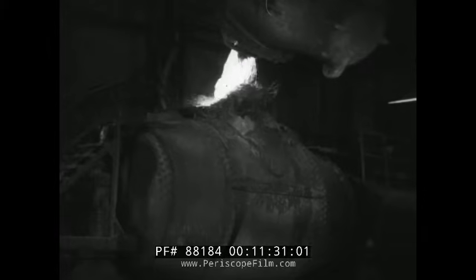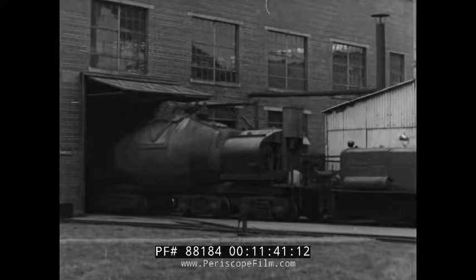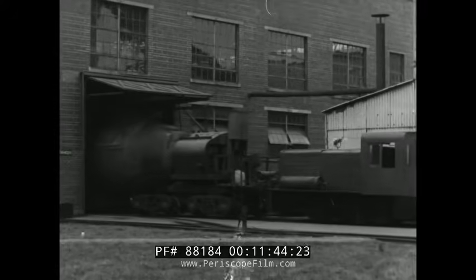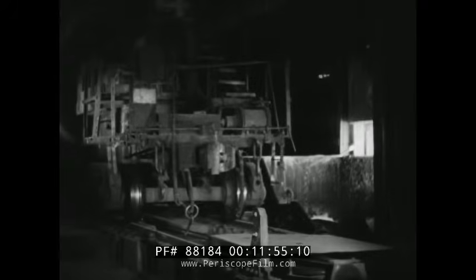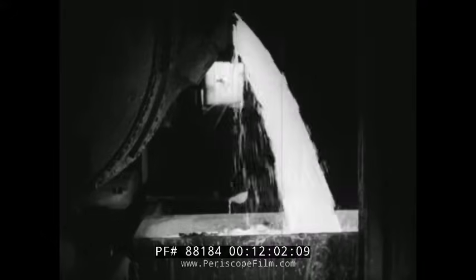The copper sulfide is blown to blister copper in these acid converters. The slag that is skimmed off goes back into process. The blister copper is tapped into ladles and then poured by crane into a specially designed hot metal car. This car delivers the metal to the company's copper refinery over a mile away. The hot metal car from Copper Cliff has arrived at the Ontario Refining Company plant with approximately 150,000 pounds of blister copper still molten. This heat is transferred to the loading furnace for further processing.